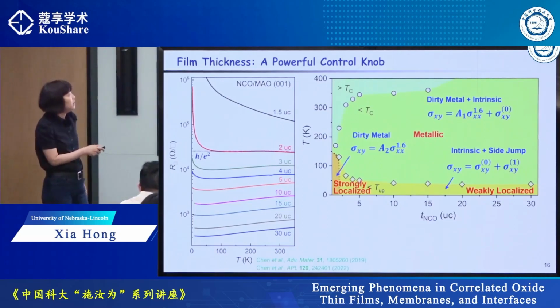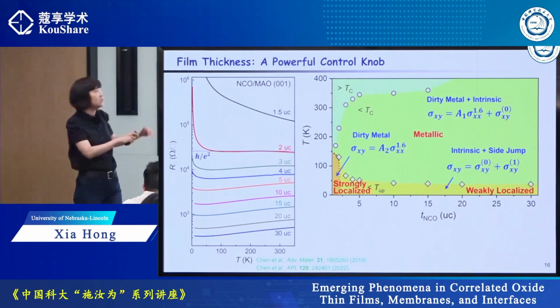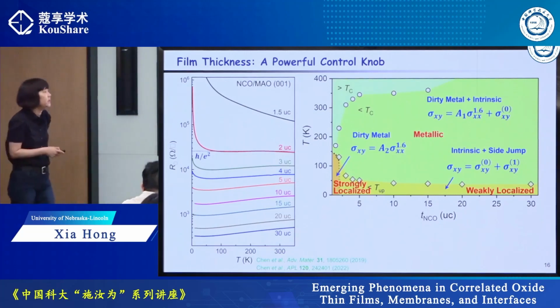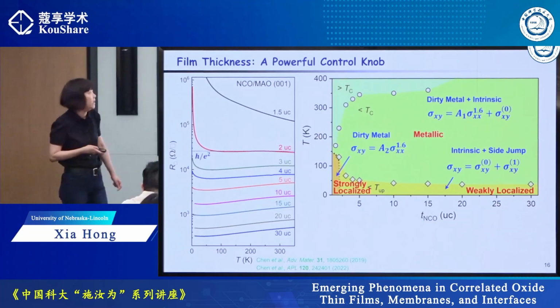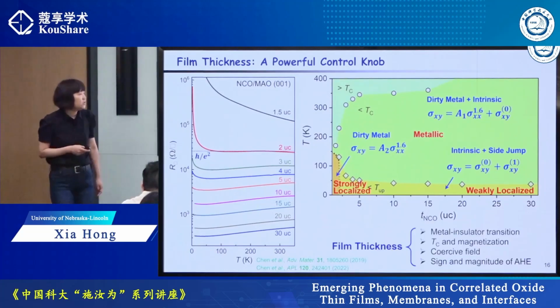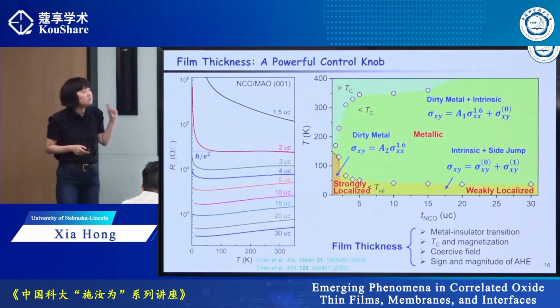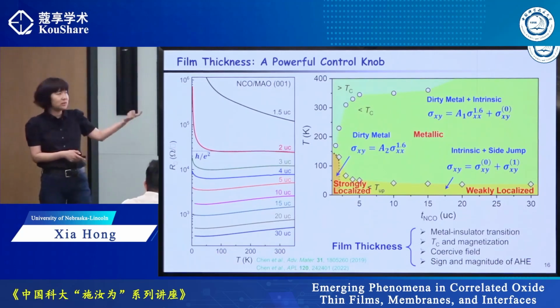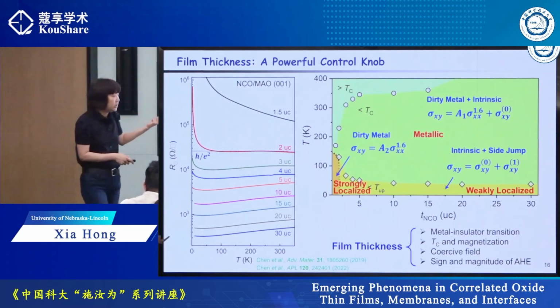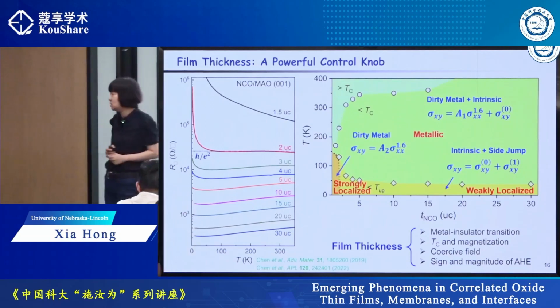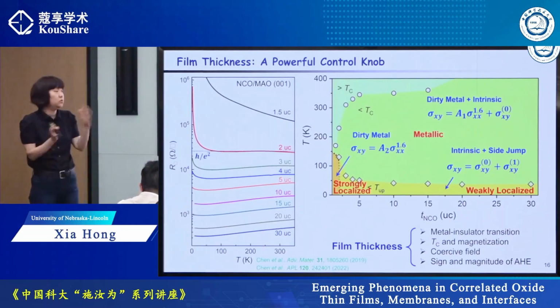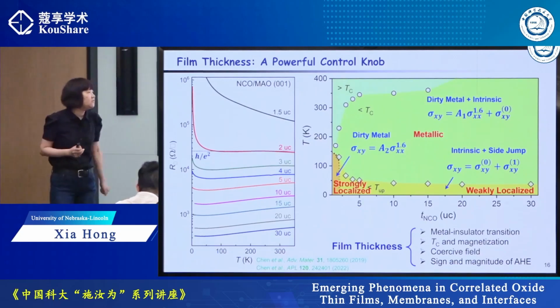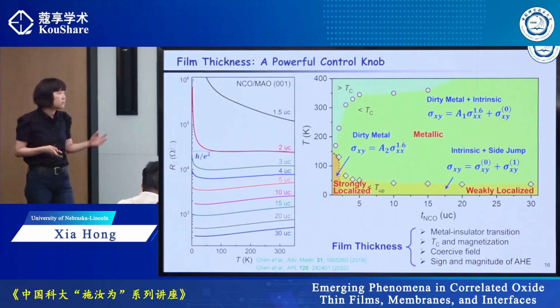In the dirty metallic region, it's actually dominated by dirty metal plus intrinsic effect. In the weak localization region, you have a constant due to either side jump or band intrinsic behavior. When it's strongly localized, it's dominated by dirty metal behavior. And you can see that for NCO, film thickness becomes a very, very important control parameter because it changes the metal-insulator transition, changes the Curie temperature and magnetization, can tune the coercive field, and can tune the sign and the magnitude of anomalous Hall effect. So basically, you can use the film thickness to tailor the magnetic behavior of NCO for different applications, either for sensors or for MTJ.